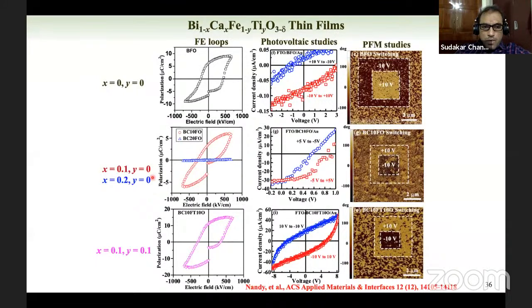So we tested the devices made using calcium and titanium. The calcium, as I mentioned, introduces lots of oxygen vacancies. The moment oxygen vacancies come, the ferroelectric nature goes down, and the inbuilt potential due to the ferroelectric domains is gone, and you see only the inbuilt potential due to the contacts come into the picture, and therefore the open circuit voltage decreases. But then we found a large short circuit current, which is a good thing. So the defects increase the short circuit current, but kill the open circuit voltage. By doing both calcium and titanium, we could retain both of them.